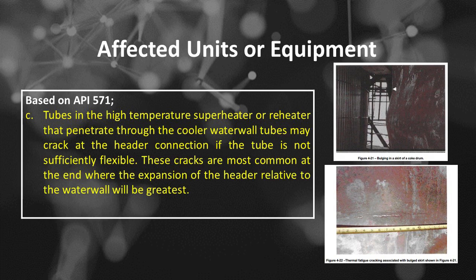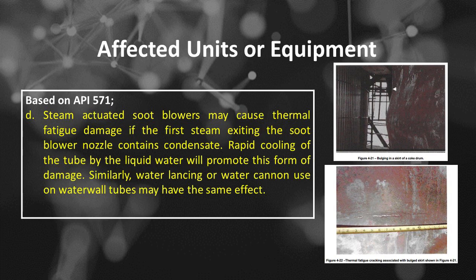The third is tubes in the high-temperature superheater or reheater that penetrate through the cooler water wall. Tubes may crack at the header connection if the tube is not sufficiently flexible. These cracks are most common at the end where the expansion of the header relative to the water wall will be greatest. The fourth is steam-actuated soot blowers may cause thermal fatigue damage if the first steam exiting the soot blower nozzle contains condensate. Rapid cooling of the tube by the liquid water will promote this form of damage. Similarly, water lancing or water cannon use on waterwall tubes may have the same effect.